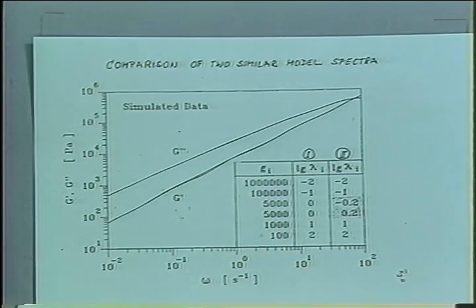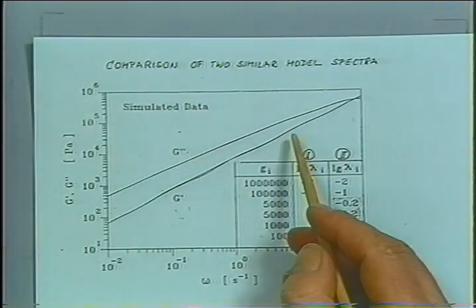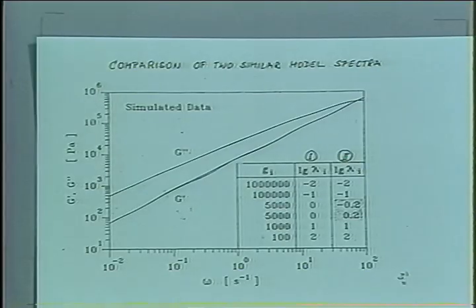So if we would have a data set without noise, our reduction procedure would give us exactly the real spectrum of that material. Okay, so it really follows everything in detail. But in actuality, we have noise, and we have to account for this noise. So that's fine. But note the waviness here. This waviness in the data is due to our artificial spectrum. It's not due to the reduction.